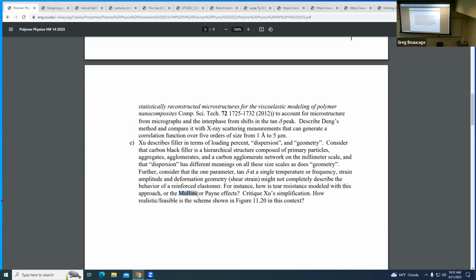Mullins effect is like when you take a balloon and stretch it, and then you blow it up, and it's easier to blow up after you stretch it. So you break up the carbon black network. They don't talk about the network because you're only looking at one size scale, just the SEM size scale. The network is macroscopic, right? So they don't mention that. And the Payne effect is related to the Mullins effect. It has to do with the strain amplitude dependence. Usually you're doing less than 1% oscillatory strain, but you can bring that up to like 10%, and you find out that the network breaks down there too, right? Frequency dependent thing. Since they're not looking at anything bigger than these 1 micron particles from an SEM, they can't see any of these things or any of the interfacial properties. So you could critique this paper that way.